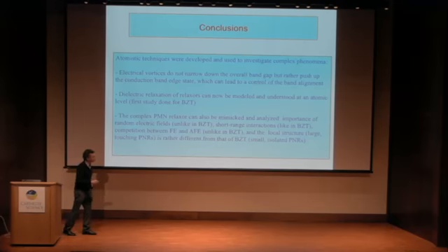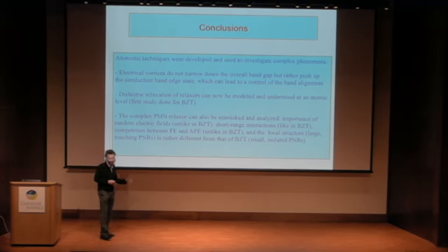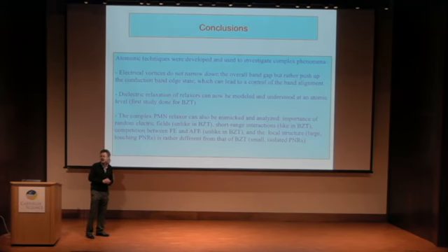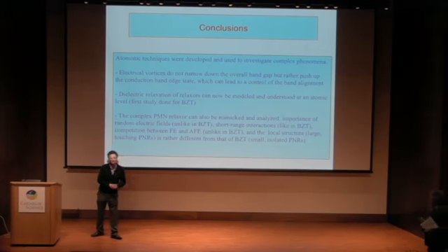BZT has small, isolated polar regions. PMN has basically large, touching polar regions. So this is very interesting. You can have two systems that are relaxers, BZT and PMN, but not at all for the same reason. So if you look inside the system, you understand that they can be different, even if they produce the same macroscopic properties. With that, I would like to thank the organizer very much for this opportunity, and thank you very much for your attention.